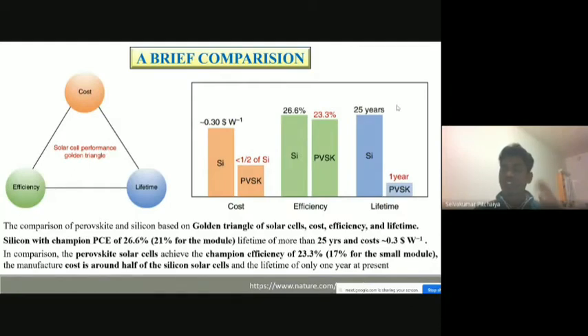In terms of silicon, it is 25 years. We can use it effectively for 25 years, but perovskite's structure is highly degradable and hygroscopic in nature, so it could withstand only about a year. As reported so far, it's about a year. And we are struggling, and we are making a lot of progress in encapsulating these devices and providing some interfacial layers to improve its lifetime.